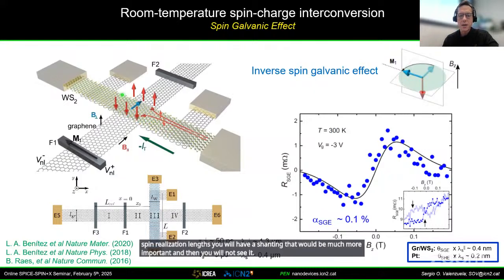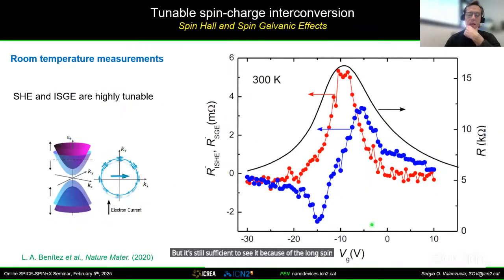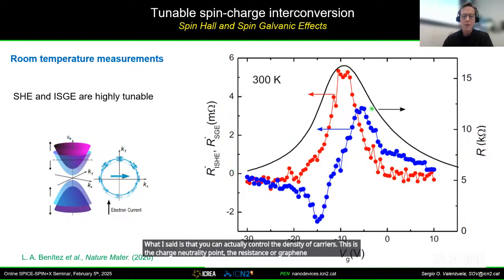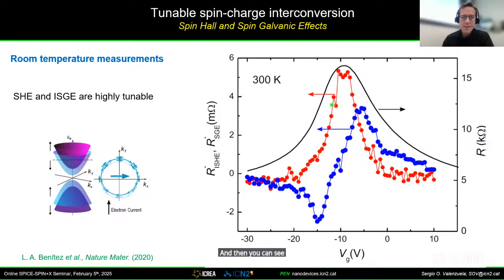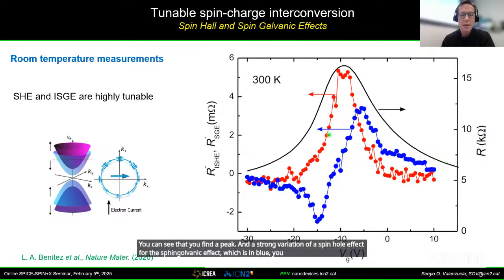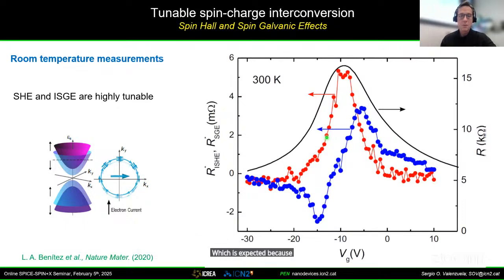Same experiment you can do with the spin galvanic effect, but now with a perpendicular magnetic field. Again, you get an efficiency which is rather low, but it's still sufficient to see it because of the long spin relaxation length. Now, what I said is that you can actually control the density of carriers. This is the charge neutrality point, the resistance of graphene underneath the transition metal dichalcogenide. And you can see that the spin Hall effect, and this is all room temperature again, you find a peak and a strong variation. For the spin galvanic effect, which is in blue, you see a change in sign, which is expected because you go from electrons to holes.